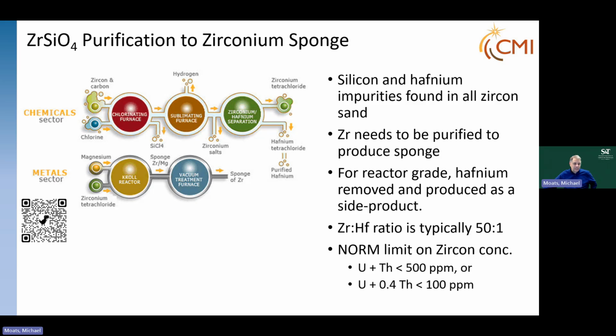When you look at it, just some cartoons. We're going to take zircon, mix it with carbon and some chlorine gas. This is the chlorination furnace. Zirconium hafnium chloride comes out. There's some purification in the sublimation furnace, which may happen here, or it actually may happen before the Kroll reactor, depending on the plant. We go through a separation. This can be solvent extraction. This can be distillation. We end up with zirconium tetrachloride and hafnium tetrachloride. The zirconium tetrachloride ends up in a Kroll reactor, where we end up with sponge of zirconium. The hafnium can also go through a Kroll reactor and vacuum induction, but hafnium can also be produced electrochemically. We'll talk about that at the end.